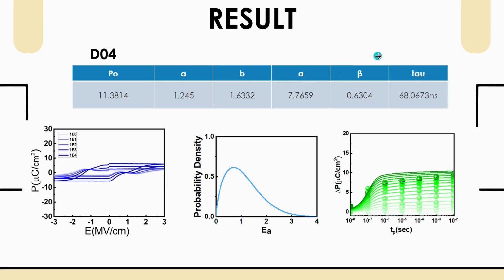And here are some results of the measurement. D04 is the sample with lanthanum doping. It had the fastest tau zero, around 68 nanoseconds, meaning it switches quickly, but the amount of charge it can hold, the polarization, was only about 10 microcoulomb per centimeter squared, which is low. Also, the switching didn't grow much after cycling, so it may not be very useful for real devices.